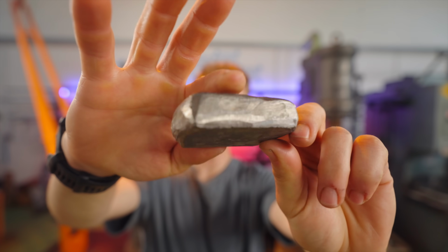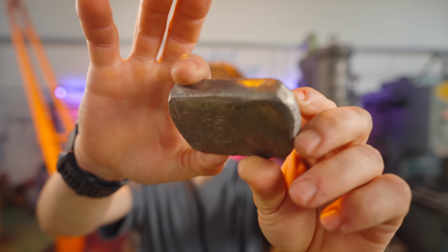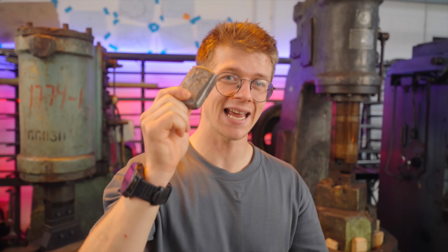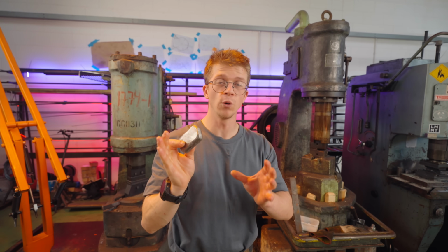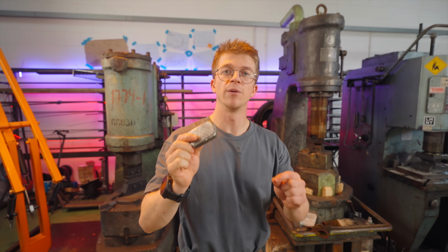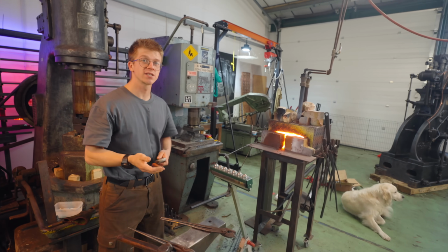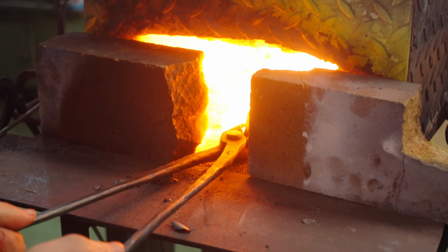The jacket eventually came off and I cleaned it up with the cupstone on that 9-inch grinder. This billet A has 125 layers. And what we're now going to do is forge it down into some round bar before twisting it. Can you twist titanium Damascus steel without it delaminating? See, that's the concern. Are the bonds between those 125 layers strong enough to withstand being twisted?